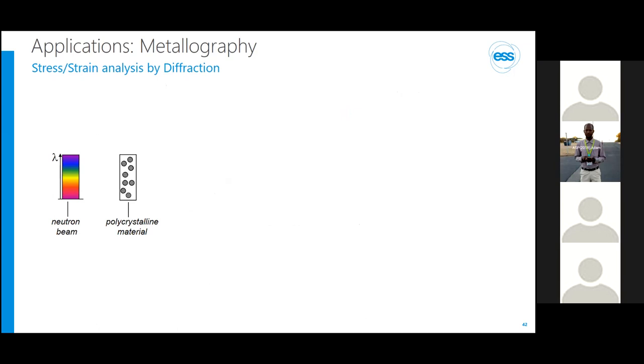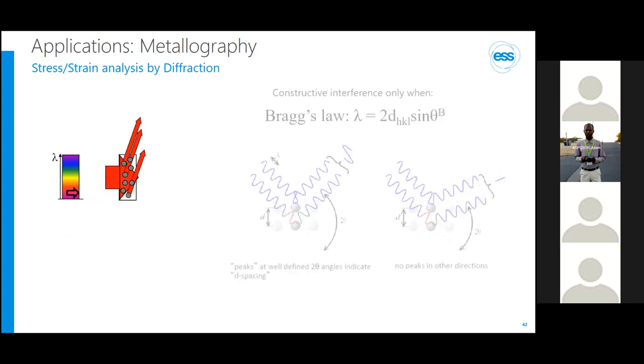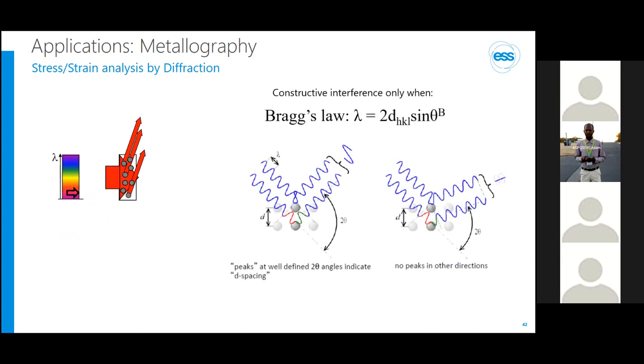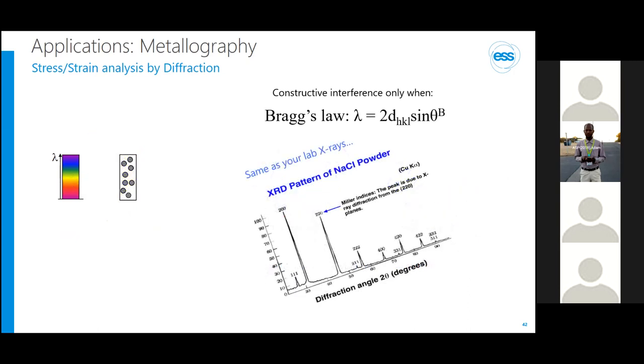And if you want to gain information about the atomic lattice structures, we can employ diffraction. So how does diffraction actually work? If we shoot monochromatic neutrons at a polycrystalline sample, some neutrons scatter according to Bragg's law at certain angles. This angle and the wavelength of the neutrons can of course be recorded. By choosing another wavelength, it will result in another angle. And by doing this, you can then obtain a full diffractogram like you would, for example, on your laboratory-based X-ray system.